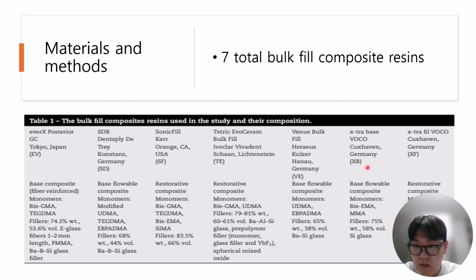And second category, the restorative type. This can be used alone to fill cavities. First example is SonicFill, SF, activated by sonic vibration to reduce viscosity temporarily. A second example, Tetric EvoCeram Bulk Fill, TE, uses a special photoinitiator for deeper curing. And x-tra fil VOCO, XF, has the highest filler content and the strongest mechanical properties. Lastly, EverX Posterior is not flowable but still used only as a base. It contains glass fibers that improve strength and recovery.